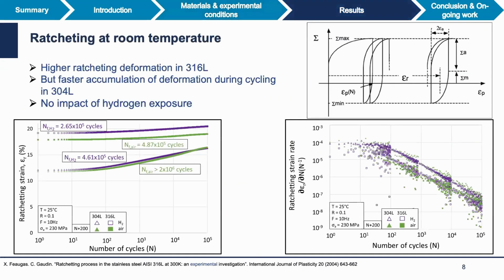So as I said, since we performed the test with a positive mean stress, that means that during the fatigue life, we'll have a progressive deformation. So here you have a comparison of this ratcheting strain as a function of the number of cycles for the 2 grades, and in the 2 environments at room temperature. And on the right-hand side, you have the data derived from these curves presenting the progressive strain rate as a function of number of cycles.